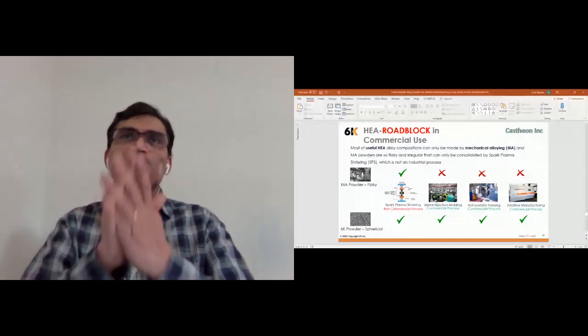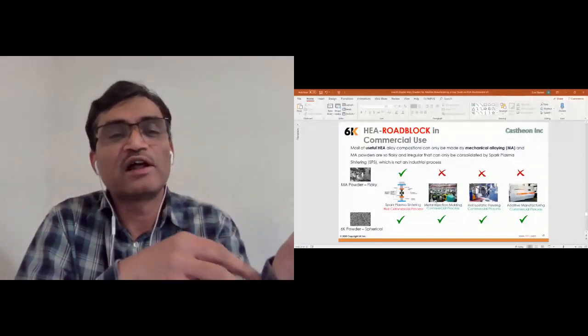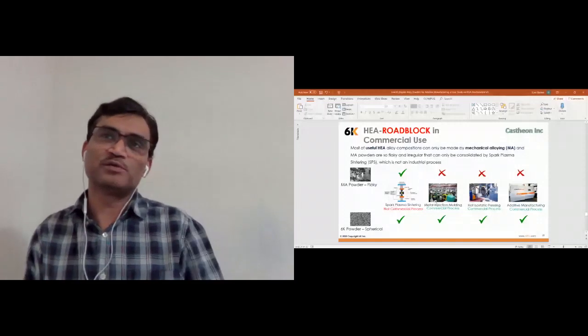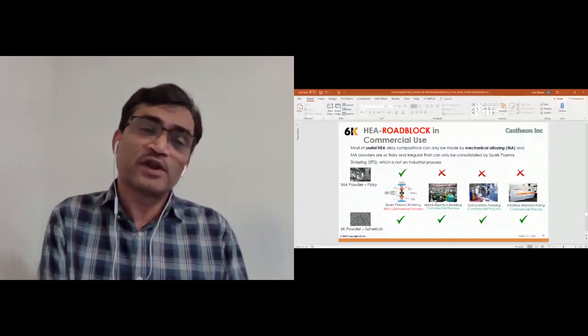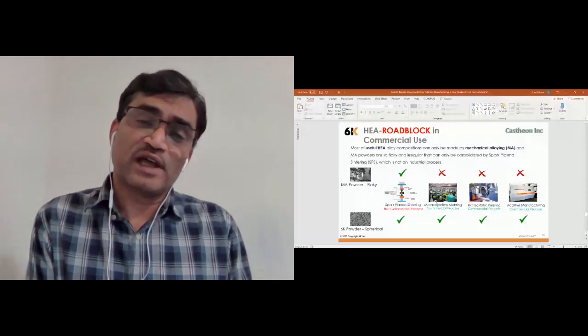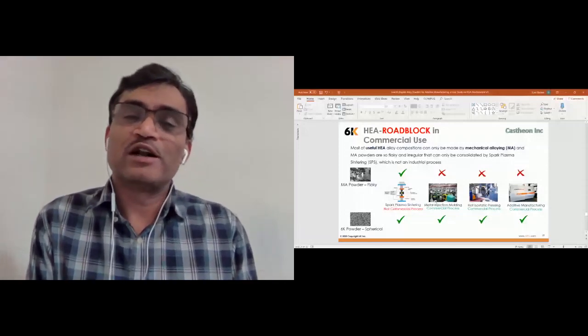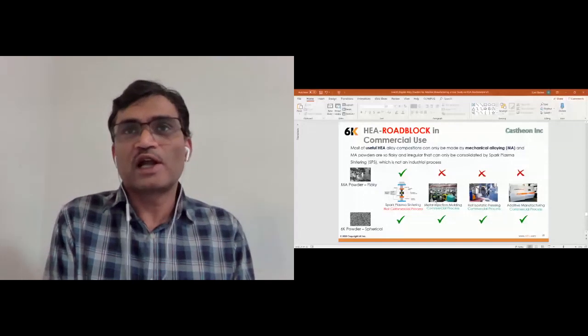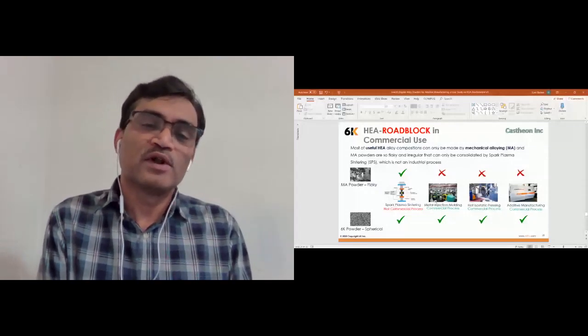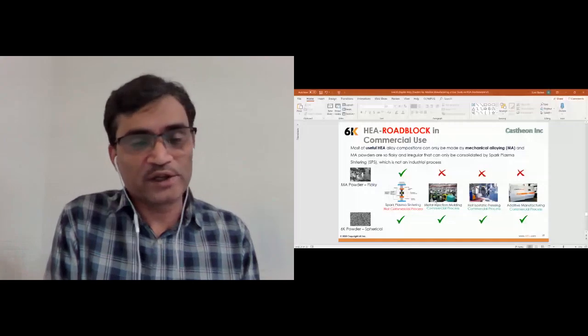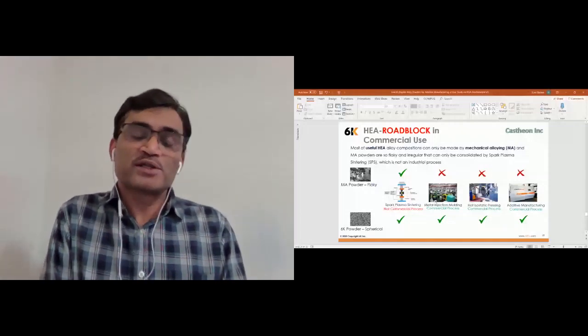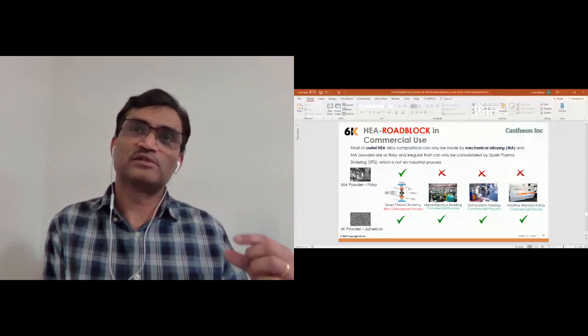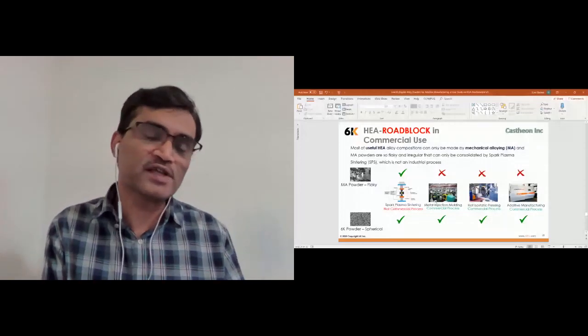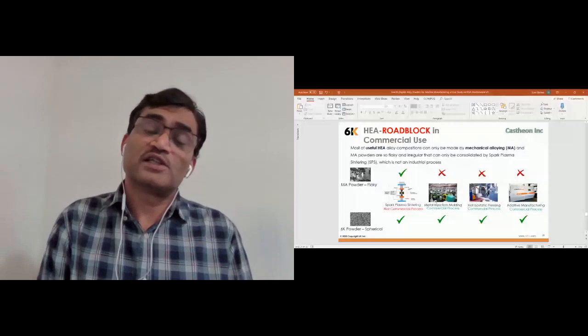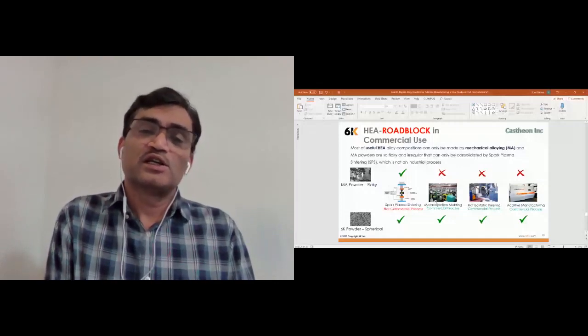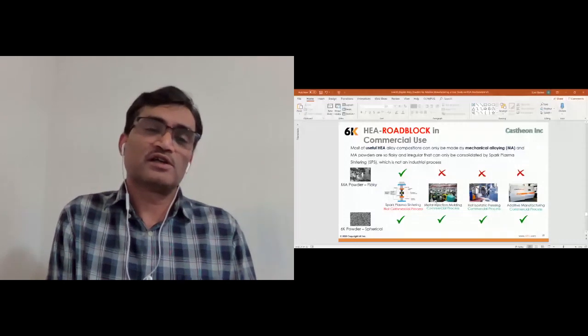Most of the useful high entropy alloys, based on the research, have at least one component which is a very low melting point element compared to the other elements, and that makes it a little difficult, or at some points impossible, to make from melt-based technologies like arc melting. It is probably possible at lab scale where we can heat very fast and cool very fast, but commercially, or in scale applications, it's very difficult to make such alloys.